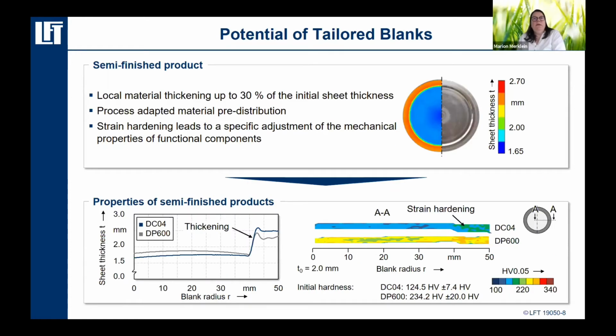But of course, doing so, we were at the beginning of the real fundamental research work. And so what we did was we investigated if we can apply such a technology on different materials, so steels and aluminum alloys, if we can give a more general indication about the maximum thickening we can realize, and how we will influence the mechanical properties of such materials. And so here you see one example for two steels, a mild steel DC04 and a high-strength steel DP600. I can tell you that also for aluminum alloys we have similar results. So in general we can say in such a rolling operation we can have a local increase of the sheet thickness up to about 30%.